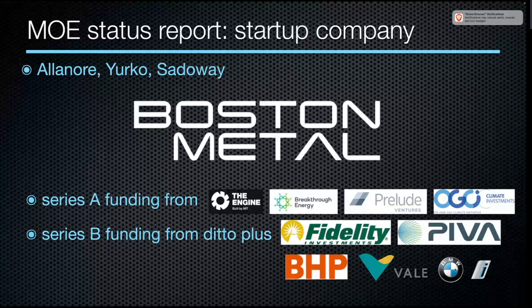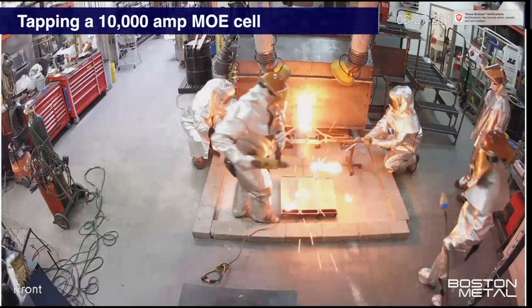So you can see that some people are starting to line up behind a practical approach to making carbon-free steel. And so we put together a team, Antoine, Jim, and I, and we designed the first freestanding cell. It was about, I think, 5,000 amperes. And this is from several years ago. Right now, we're up to 25,000 amperes, but this was a 10,000 ampere cell that I have a movie for. And you're going to see.